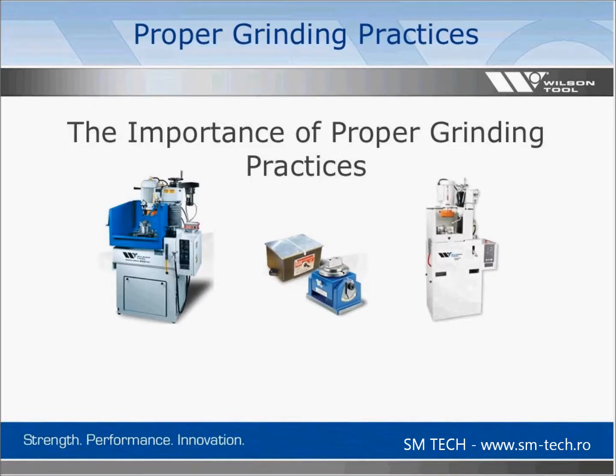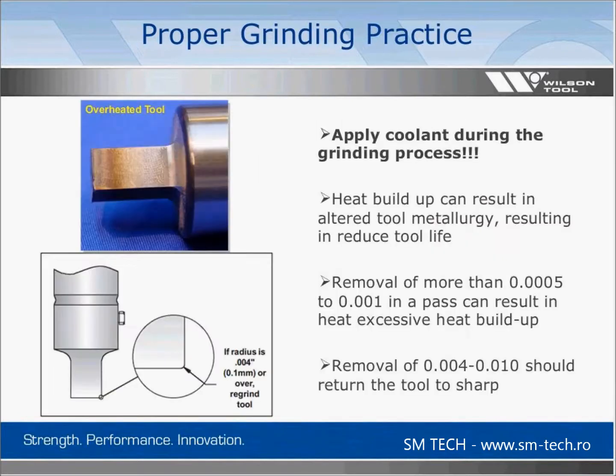We're going to start with proper grinding practices. Proper grinding practices is one of the most basic functions that you can perform to ensure that you're getting the most life out of your tooling. The number one most important thing when grinding your tooling is to apply coolant to the tool during the whole grinding process. Without applying coolant, heat buildup can result in an actual change in the metallurgy of the tool, and it can drastically affect your tool life.